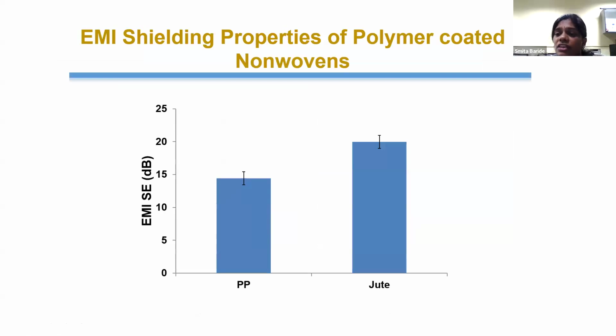Now for these samples, we have measured the shielding effectiveness. The shielding effectiveness can be converted to shielding efficiency. 20 decibel shielding effectiveness means around 99% shielding performance. 15 dB means 95%. Basically, there is one logarithmic formula based on which we can convert this shielding effectiveness to shielding efficiency. With the conducting sample, we are supposed to achieve a minimum of 10 dB shielding effectiveness. Only then can we say that there is a 90% attenuation of electromagnetic signal.